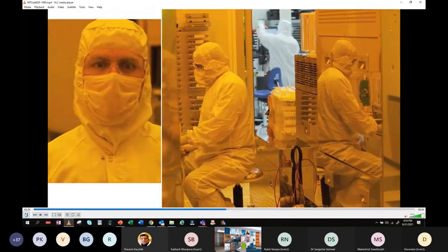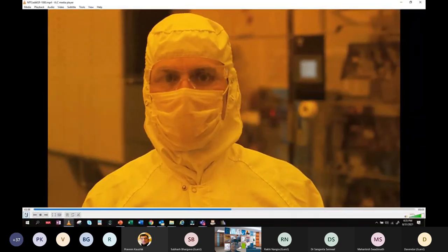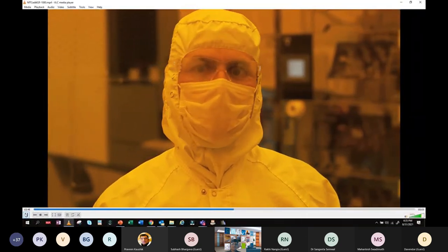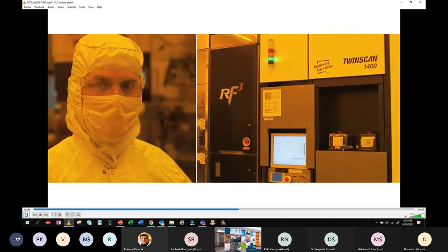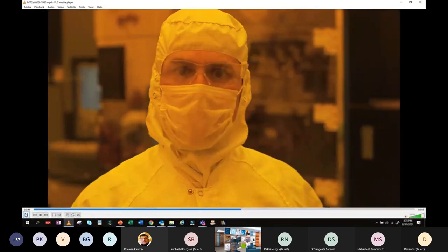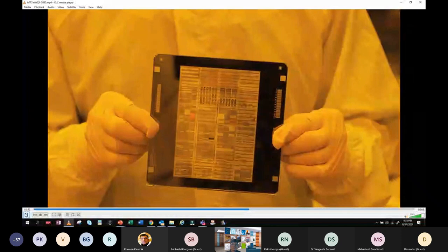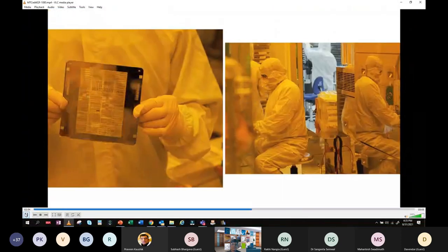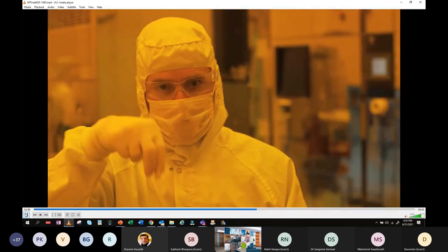Lithography is the process by which circuit patterns are printed on the wafer using a tool called a scanner. To enable us to simulate our customers' advanced chip structures, we've installed a complete lithography cell, including an immersion-capable scanner and a track, a tool that applies and develops light-sensitive films on the wafer. The circuit features that will appear on each layer of the chip are held on a photomask, which is loaded into the scanner and then printed stepwise hundreds of times across the wafer.